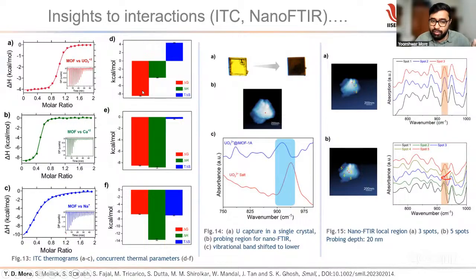So the largest decrease in the free energy, that is in the red band, and the increase in the entropy, is the ideal situation for cation exchange within a particular assembly or framework, and that's why ITC helps us understand why the uranium exchange is higher, because it helps us to understand the dynamics. And then what we did particularly after this, we went for uranium capture in nano-FTIR. Nano-FTIR is one of the best techniques to understand 2D and 3D material dynamics in vibrational spectroscopy. So how the functional groups are oriented, how their phases are analyzed, and at such a nano level, like 10 to 20 nanometers, is just a layer-by-layer difference in the molecular arrangement.